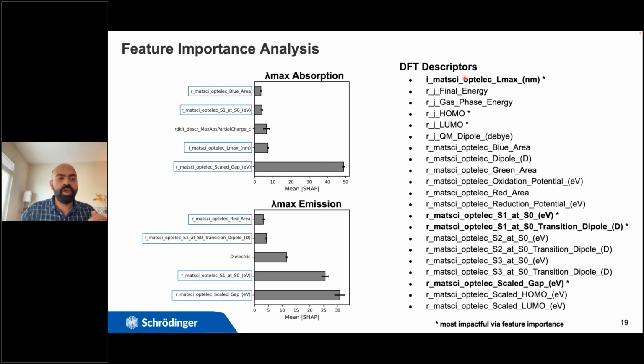optical properties. For example, for the lambda max absorption, the most important property was the Scaled Gap and the lambda max absorption calculated using DFT, which is not surprising. Similarly, for lambda max emission, the Scaled Gap was also an important property. So this shows you the power of combining DFT descriptors for the optical properties of chromophores and OLED molecules as